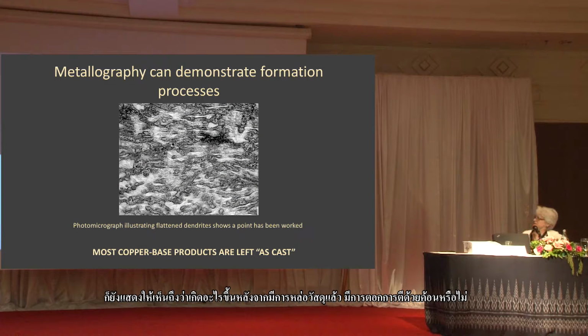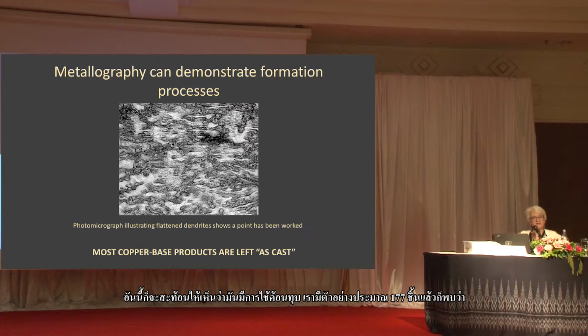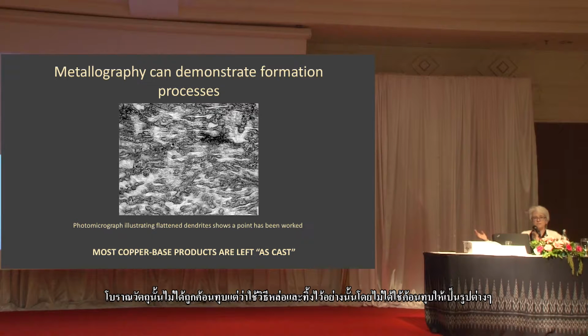Another thing that the metallography shows is evidence of what happened after the object was cast. Was it just left as what they call as-cast? Or was it hammered? Was it heated up and annealed? This particular image shows the flattening of the dendrites, which shows that this particular artifact had been hammered. But with our large sample, 177, we found that most of the copper-based artifacts were not hammered or annealed. They were left as cast. That's very interesting because it's totally different from what was going on in Europe at the same time, where hammering and annealing was the standard practice.